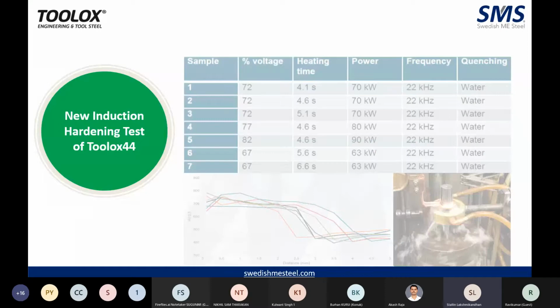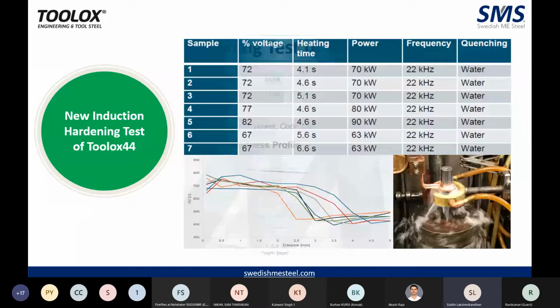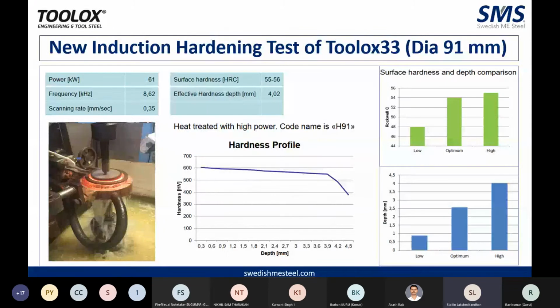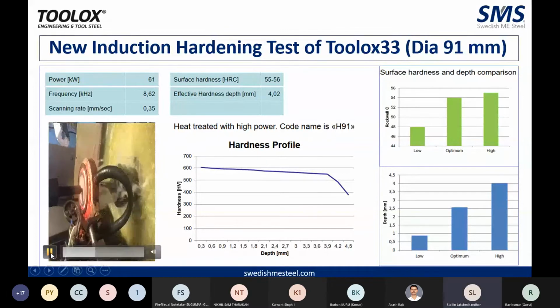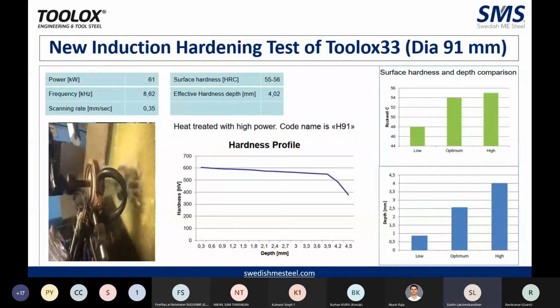So this is the new induction hardening test that we have done for Toolox 33 in 91 dia. You can just see the process, how it's been done. As you see, for the different parameters of induction hardening, even with Toolox 33, you can achieve 55 to 56 HRC with an effective hardness depth of 4.02.